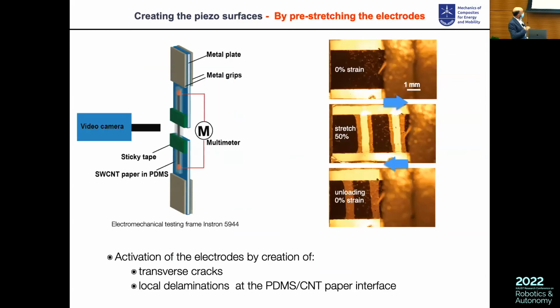And then what you can do is take these conductive films of CNT and introduce cracks in them. So you activate them. That means you pull on them, and then you crack the film. So you introduce what you call transverse cracks and delamination, that is separation between the CNT and the PDMS. So this is the activation phase, and then you unload. That means here you come back to your initial electrode, but without residual strain. You just unload the system. The cracks are here, but they are closed.